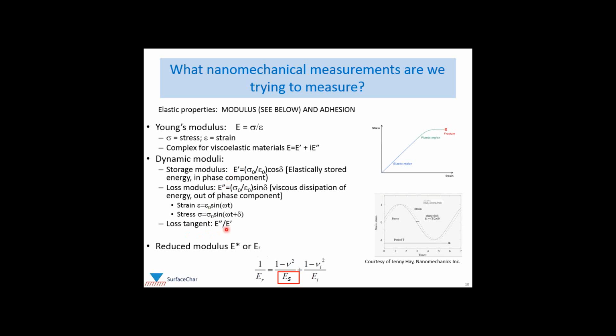Now, you also may refer to or read about the reduced modulus, which is actually what we're mostly measuring in AFM and those nanoindentation measurements. The reduced modulus is the combined modulus of our tip and our sample, where nu is our Poisson's ratio and E is the modulus. So in all of our measurements, this is really what we're measuring. And then we have to extract out this sample modulus by knowing the Poisson's ratio and modulus of our indenter and Poisson's ratio of the sample. So it's important terminology here, and you need to make sure that you understand what modulus you're measuring and what you're comparing it to, especially if you're comparing with literature.